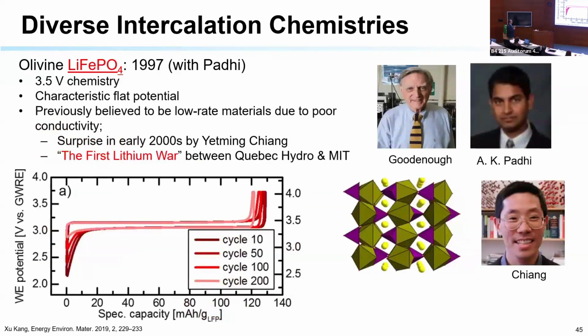So what are other discoveries that John Goodenough made? This lithium iron phosphate. This was a huge discovery. Why was it a huge discovery? Because cobalt and nickel are actually very expensive metals. Cobalt is even more expensive than lithium, and if you look at the reserves in the world, it's 10 times smaller than lithium. So it's a very expensive element. So he developed this material that uses iron, which is pretty cheap, and phosphorus, which was pretty cheap.